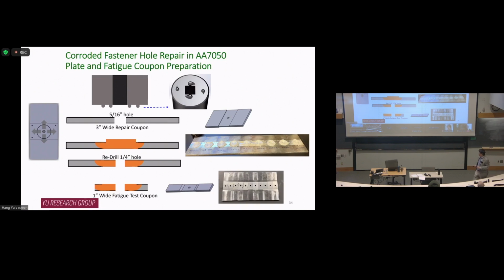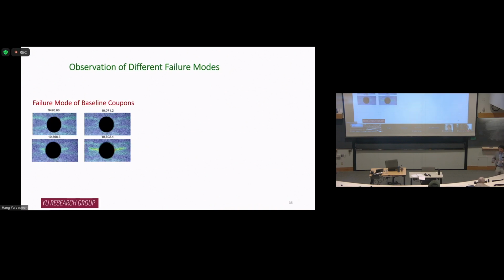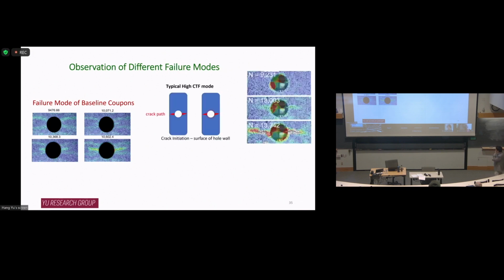I'm not allowed to show you all the detailed data, the curves, but I can give you a qualitative description of what's going on. When you have a pristine material and do fatigue testing with a hole, eventually your crack will propagate in the horizontal direction because of the tensile stress. If you do a good repair like this, where we develop a recipe, we also get the same failure mode like this.